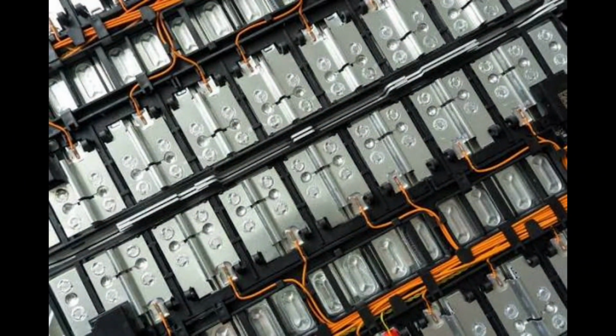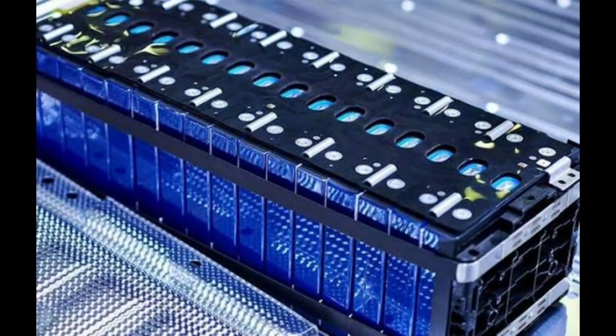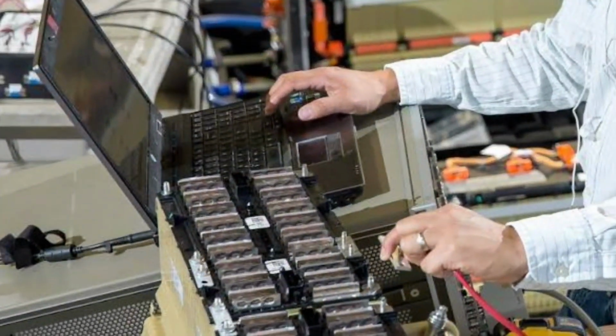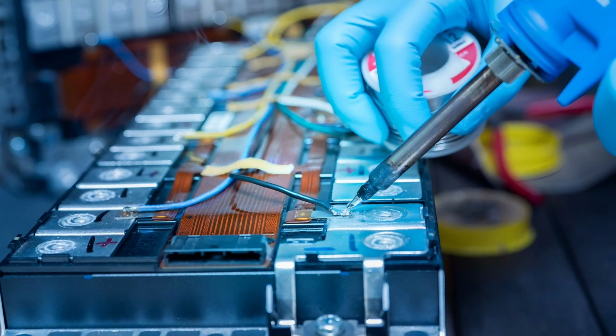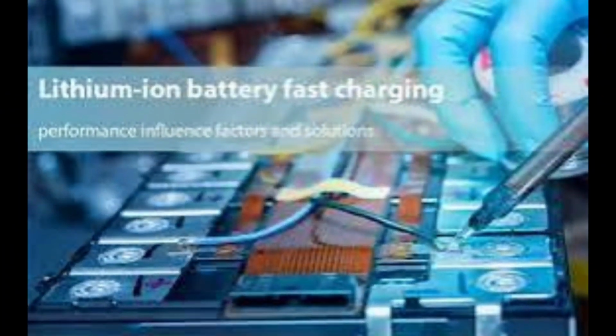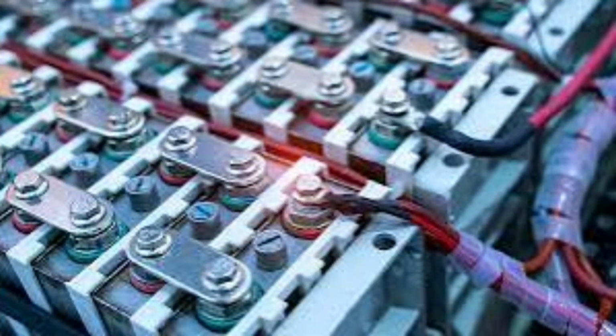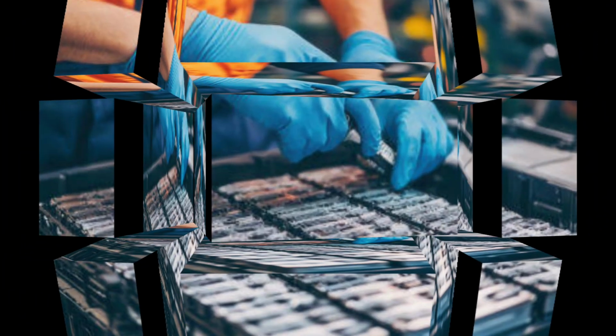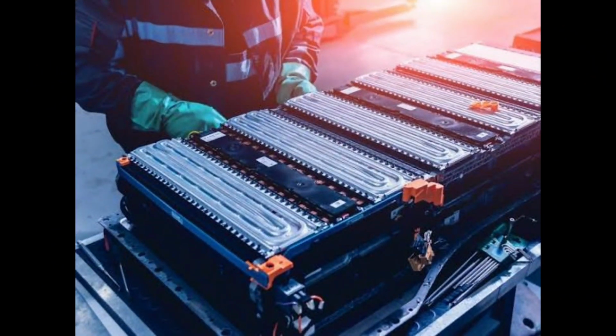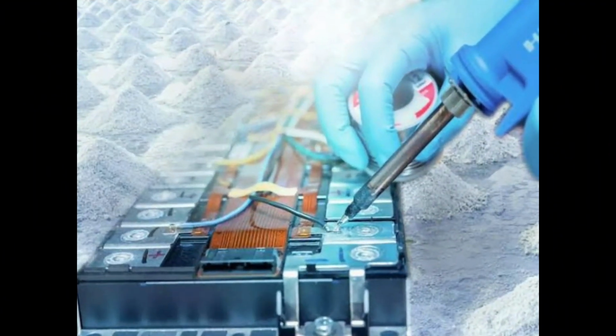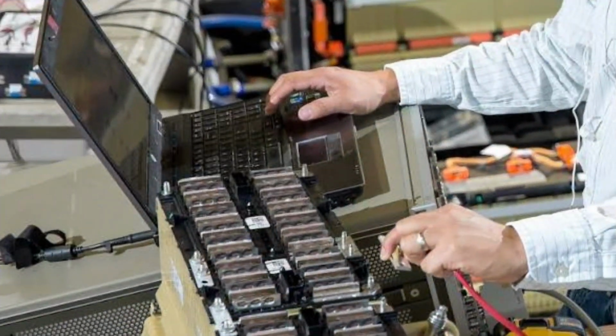Faster battery production insights. According to the researchers, the method could reduce trial and error steps in battery manufacturing by allowing developers to evaluate coating conditions directly from the slurry stage. This method can identify promising coating conditions using less than 1 milliliter of slurry, with each measurement completed in about 5 minutes, Shitanda said. The approach could also help battery manufacturers reduce material waste and shorten development cycles, as demand for lithium-ion batteries continues to grow across electric vehicles, electronics, and energy storage systems.